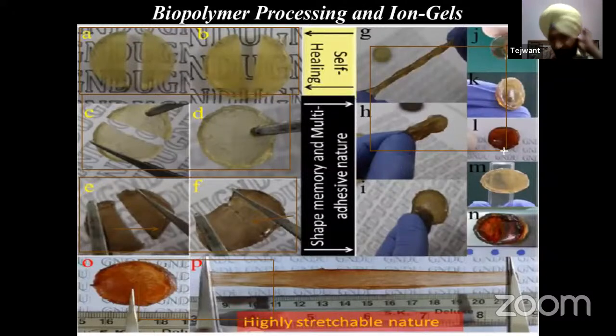So we have shown that the prepared Ionogel was capable of adhering on paper, on glass, on quartz, mica and steel also. Further, the stretchability of the gel was quite amazing. The gel could be stretched to at least 10 times its original diameter. One can stretch the gel to 10 times its original diameter.